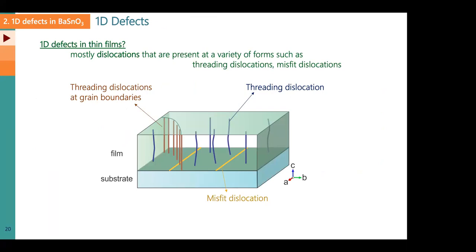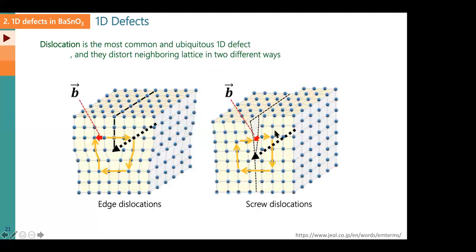In crystals, very often you have these one-dimensional defects called dislocations. If you grow the crystal, they often go from the substrate to the surface, which is why they're often treated as threading dislocations. You can see plenty of them at the grain boundaries. Here is what a dislocation is. If I have an extra plane in this crystal and I take a loop, you will see that there is an extra plane, and the edge of this extra plane is the dislocation core. Or you can have a screw dislocation. If I take a crystal, cut it and slice it, you get this type of effect, called a screw dislocation. Your crystal basically looks like a screw, and the core of that screw is your dislocation.